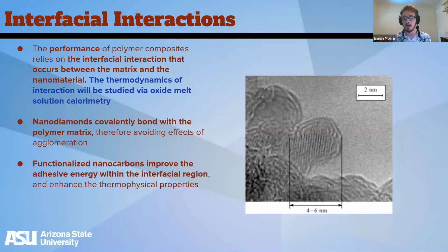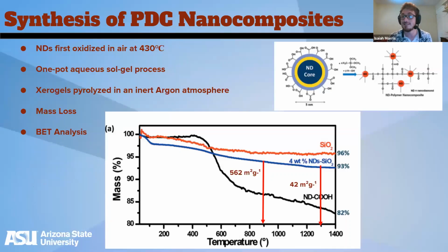And this covalent bonding yields a greater dispersion of the nanodiamonds, essentially trapping them into little cages, therefore avoiding those effects of agglomeration and overcoming those van der Waals forces. And coming back to this idea of functionalization, when you actually functionalize a nanocarbon, you end up improving the adhesive energy within that interfacial region, as well as enhancing the thermophysical properties. So, of course, the first logical step of synthesis would be to functionalize the nanodiamonds.